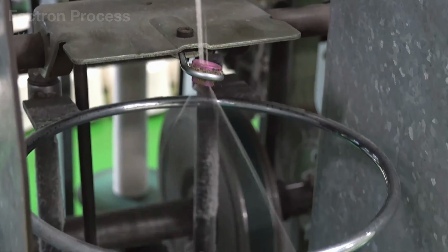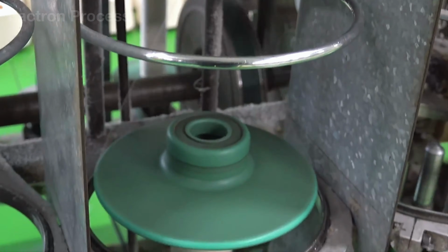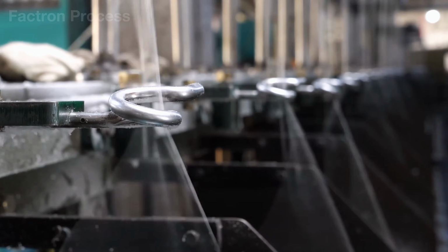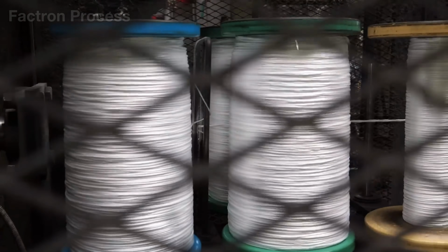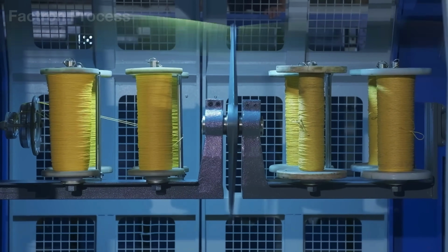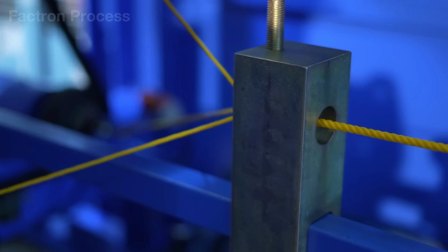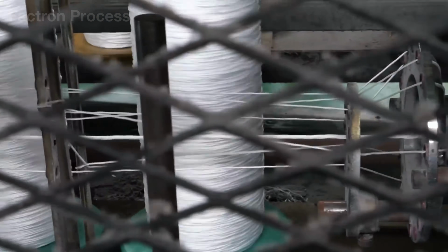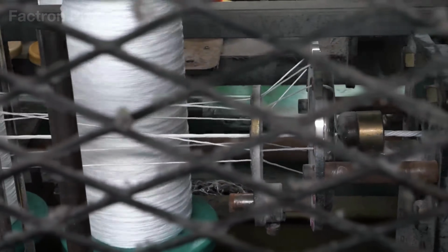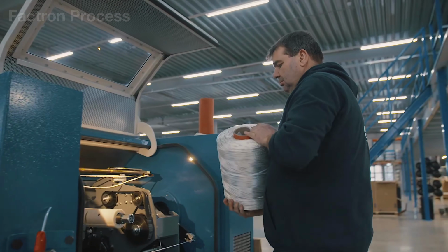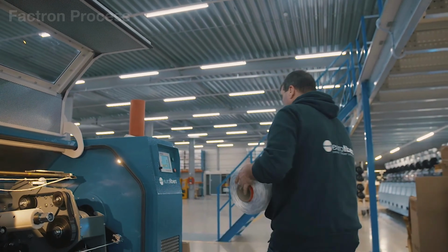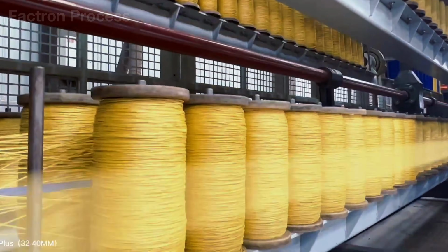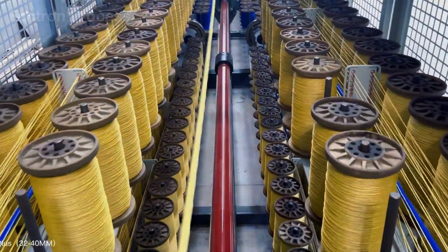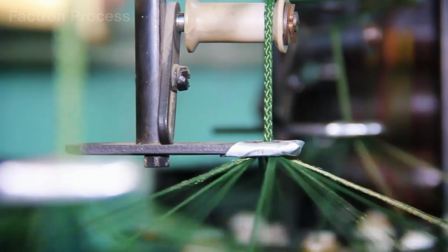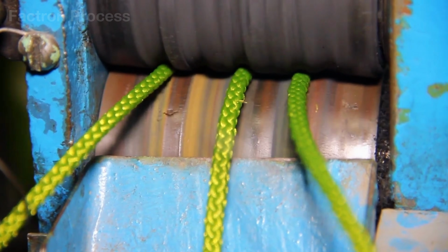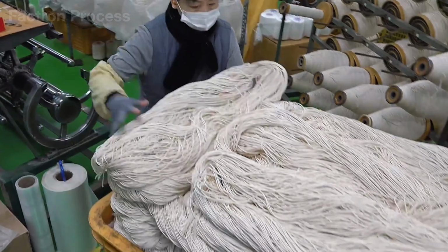The spindles typically rotate at 500 to 3000 RPM, continuously twisting the fine strands together. The twist level is critical. For synthetic ropes, the twist pitch typically ranges from 1 to 4 inches per turn, depending on the desired rope diameter and flexibility. If the twist is too loose, the yarns will fray easily and distribute loads poorly. If it is too tight, the yarns become stiff, difficult to bend, and lose flexibility. By the time they leave the machine, the fine individual filaments have been transformed into thicker, stronger yarns with significantly greater load-bearing capacity.